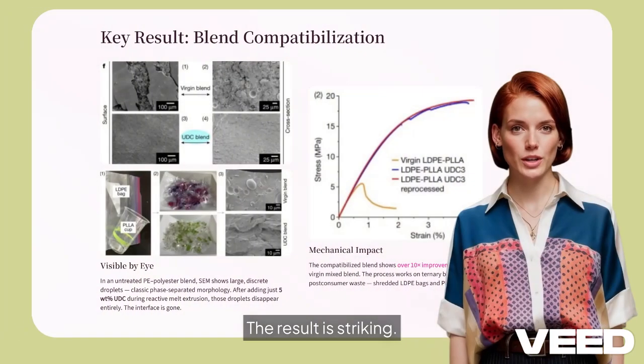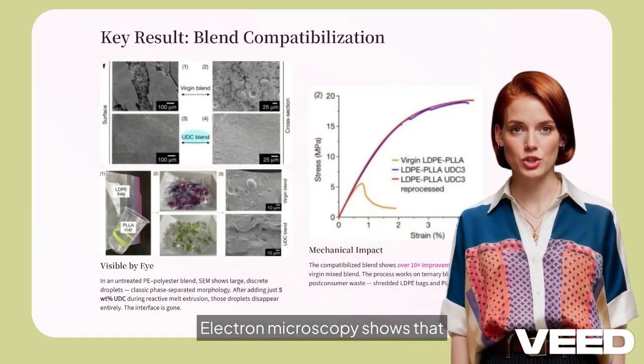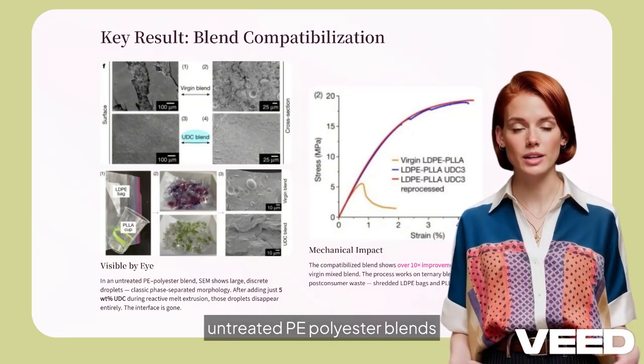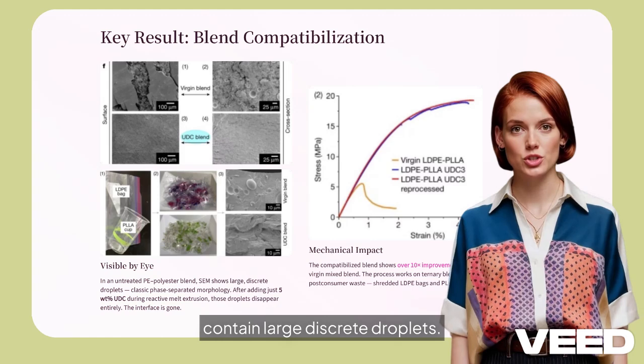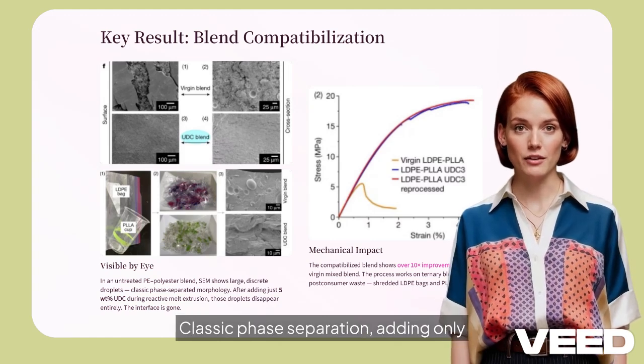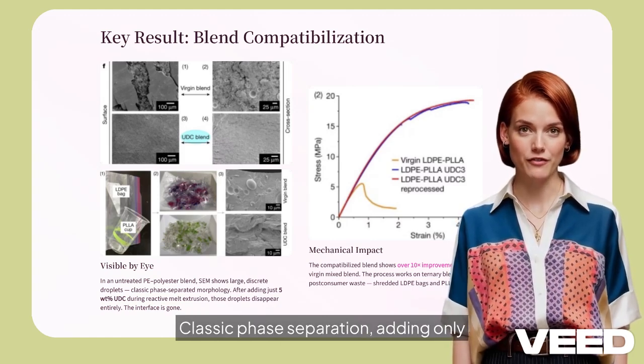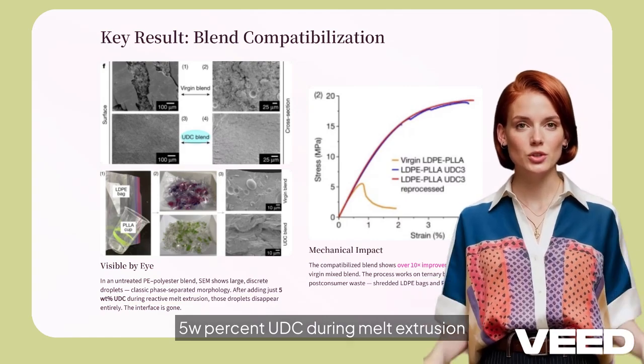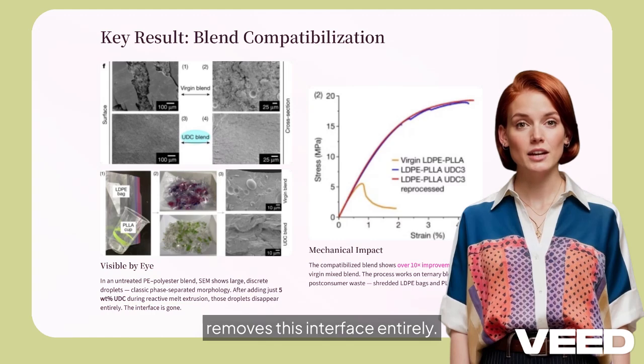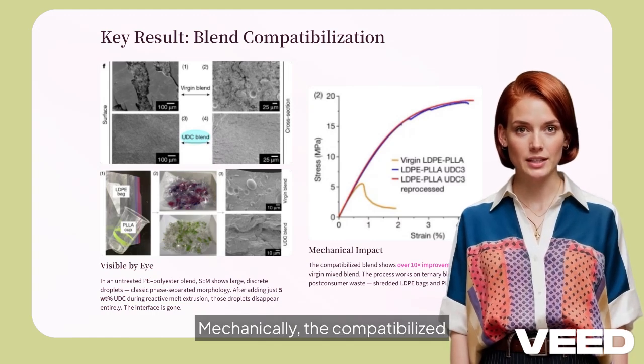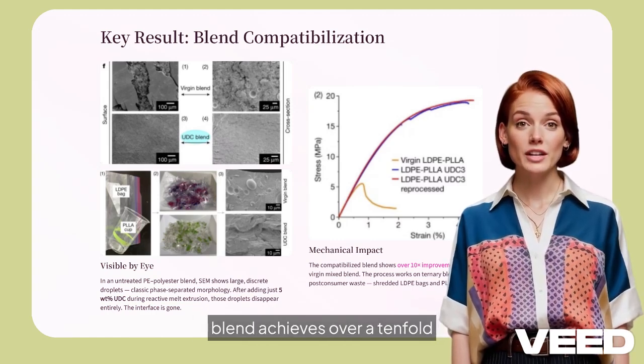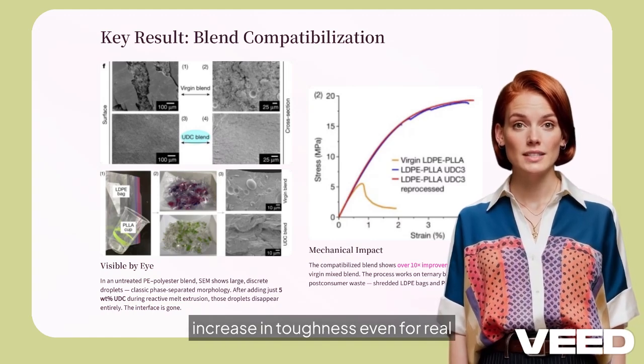The result is striking. Electron microscopy shows that untreated PE-polyester blends contain large, discrete droplets. Classic phase separation. Adding only 5% UDC during melt extrusion removes this interface entirely. Mechanically, the compatibilized blend achieves over a 10-fold increase in toughness, even for real post-consumer waste streams.